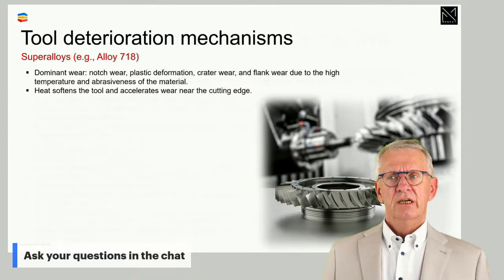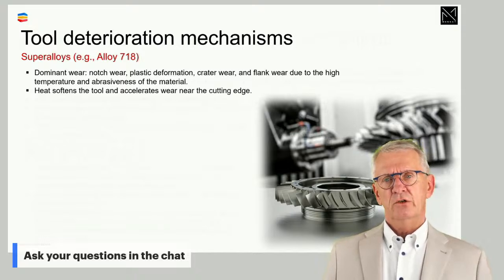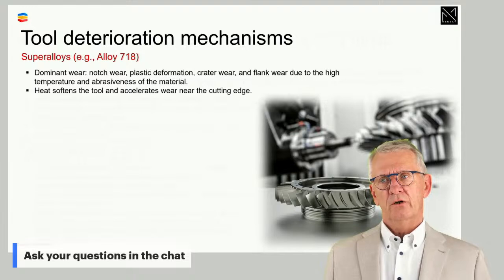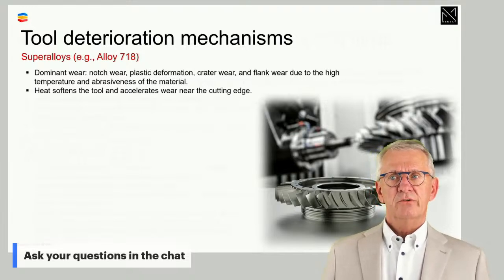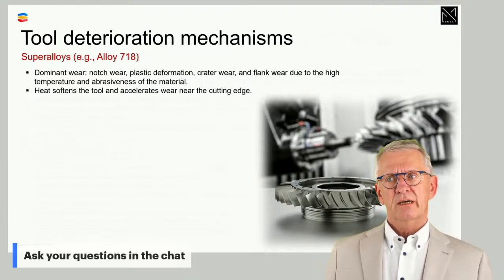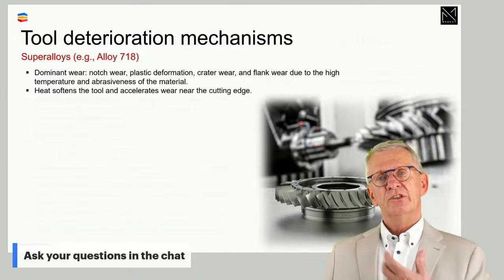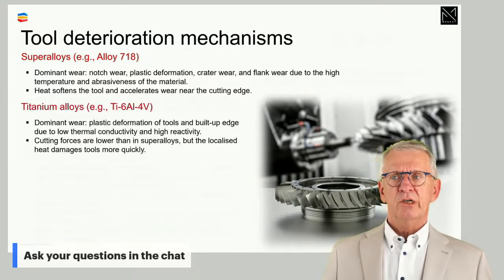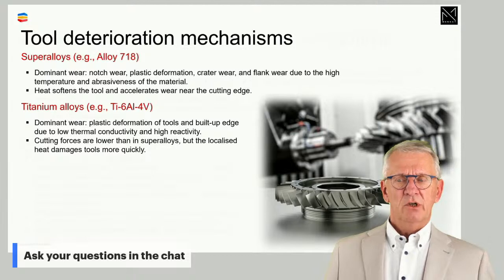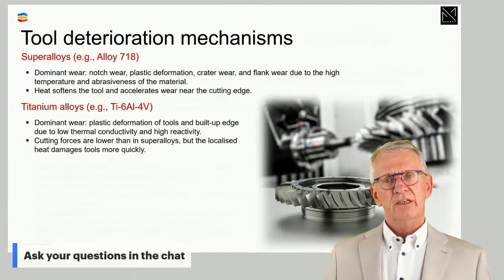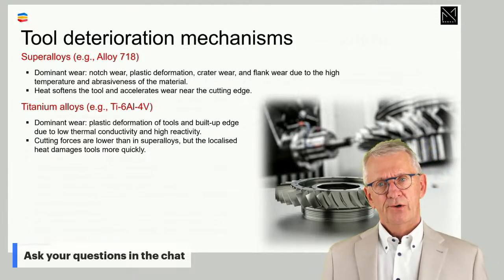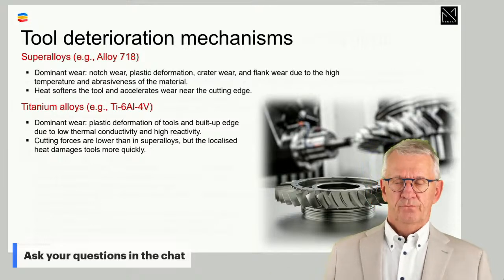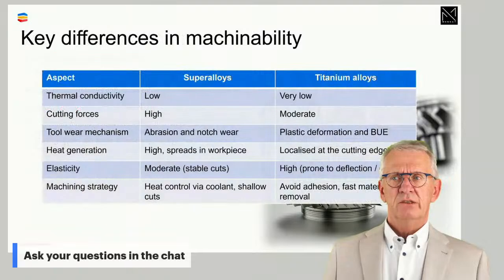better approach. Tool deterioration. Cutting edges when being used in titanium or in superalloys look different. Dominant wear in superalloys is notch wear and plastic deformation, but you will see all the other wear patterns also appearing, where in titanium alloys you see more plastic deformation and build-up edge wear in general. That is what we notice there.